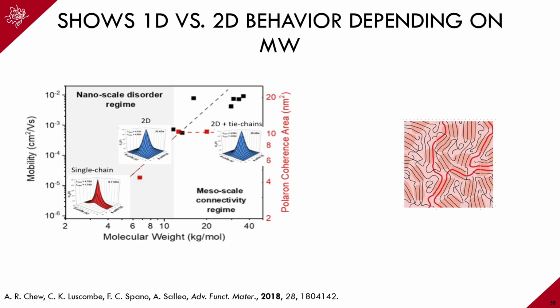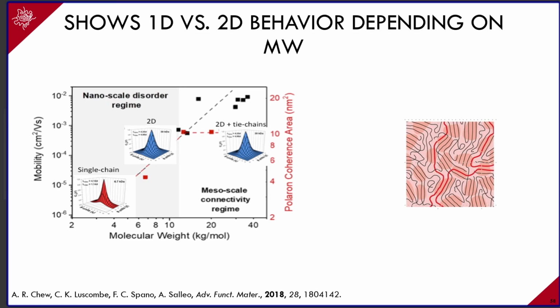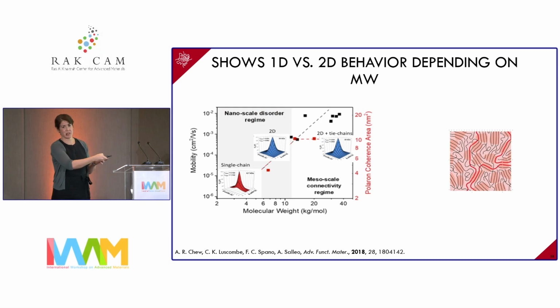When the molecular weight continues to grow, we actually reach a region where the degree of delocalization doesn't change, but the charge mobility continues to go up. And this is where the tie chains are really coming into play to affect the charge mobility that we see. But regardless, for a classical polymer like P3HT, the cartoon diagram we draw is accurate in terms of describing the charge mobility.